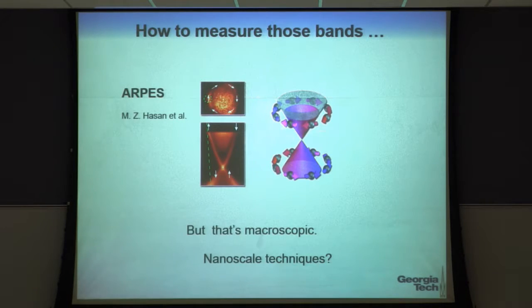And so the structure near the Dirac cone looks kind of like this. The spin direction is connected. It's perpendicular, effectively, to the k direction. That gives you a chirality up here and the opposite chirality for states down there. Great. Well, ARPES is wonderful, but it's a macroscopic technique.